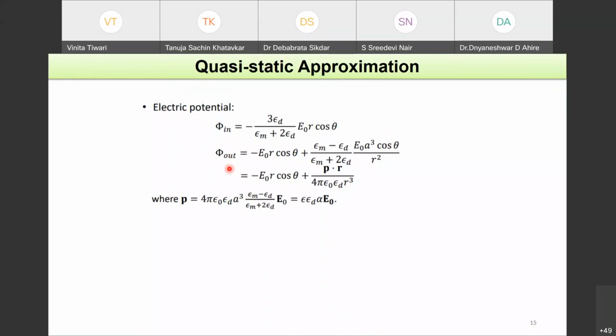And when you obtain the expression for the potential outside the nanoparticle, you will see that there is a component, this is the incident electric field, and there is something new coming up here. Okay, so what is this term? p dot r over 4 pi epsilon naught epsilon d r cubed. So this is basically the polarization of the dipole that is getting created. Okay, and you can express this using epsilon d alpha epsilon naught, where alpha is the polarizability of the particle.